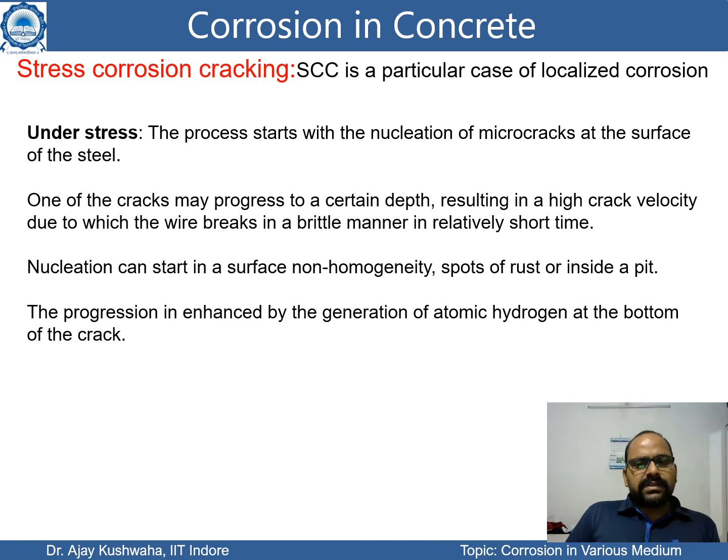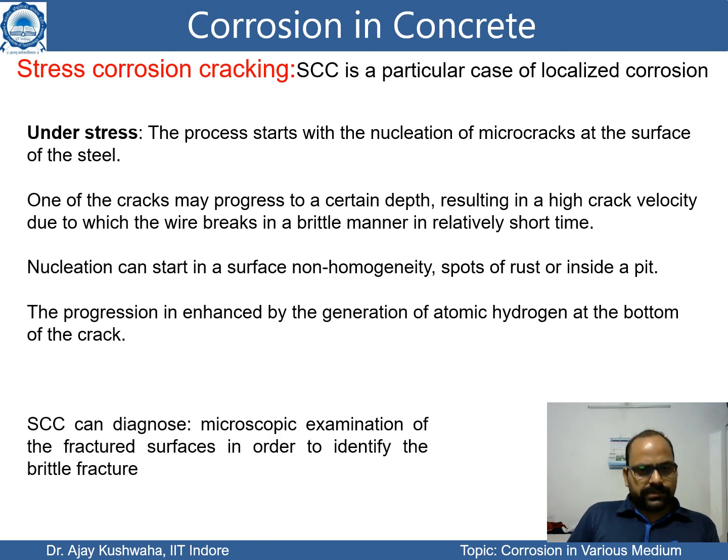Progression is enhanced by the generation of atomic hydrogen at the bottom of the crack. So depending upon how much hydrogen is generated, the progression depends. Initially it happens at the surface only, but how it will progress through the structure depends on the generation of atomic hydrogen. If you want to diagnose, then microscopic examination of the fracture surface is required in order to identify the brittle fracture. So it's a little bit tricky. We have to do the microscopic analysis.